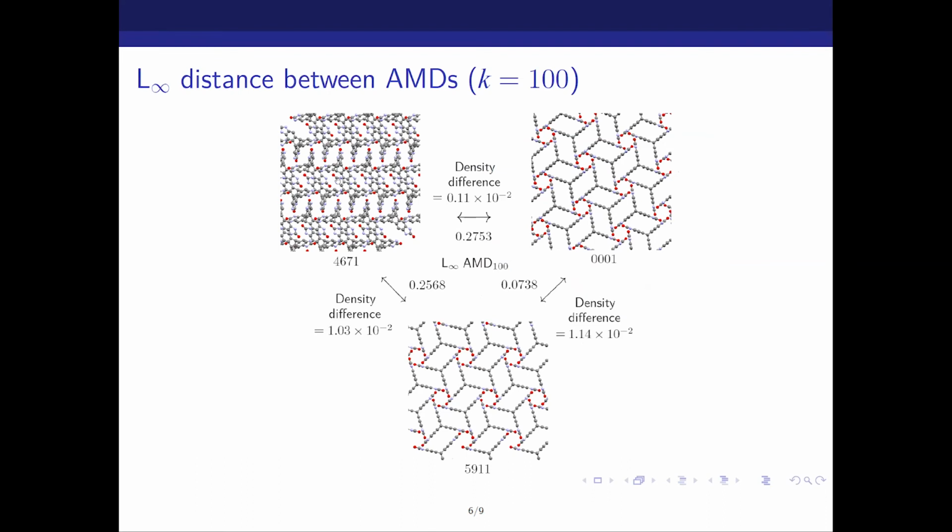And I've picked some other structure here, which is not related to either of them in terms of actual structure, but just so happens to have a very, very similar density to this. And this is just what happens because density is a single value measure. It only takes on a reasonable range of values. So if you have a big data set of 6,000, you're bound to have 2 that overlap that aren't related. And you can see that in the density differences in the triangle.